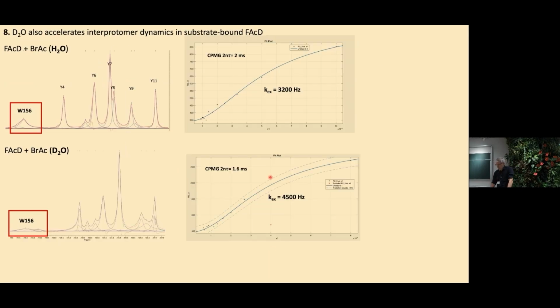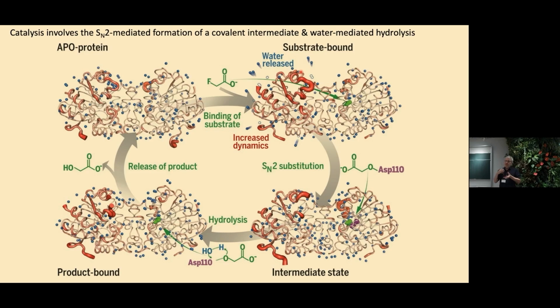And so the other question would be, what happens to the dynamics in the presence of a substrate analog? So we can add a substrate analog, which means it looks like a substrate, but the bond can't be broken. So we throw that in, and what you'd expect is if you throw in a substrate or a substrate analog, dynamics would take off, and they do. All right, so these are two measurements here at different sites, 3,000 and 4,500 times per second. But what's interesting is that when we again replace H2O with D2O with substrate analog present, the dynamics become faster. Okay, so that's an experimentalist way of saying that water is important for allostery. Okay?